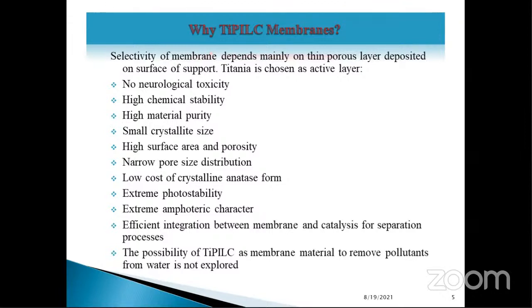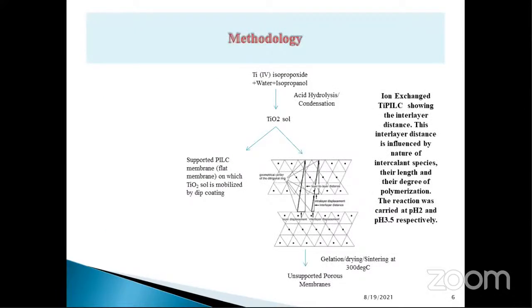Also, this possibility of using this titania pillared clay material as membrane has not been explored till date. The methodology that we have adopted is the simple sol gel process in the laboratory. We have used titanium 4 isopropoxide as the starting precursor, and added water and isopropanol to it, which underwent acid hydrolysis at 2 different pH, that is pH 2 and pH 3.5.